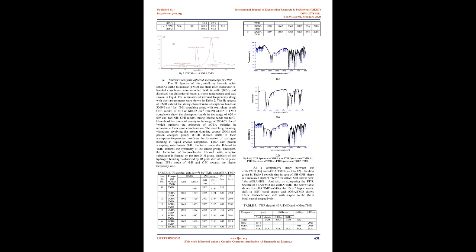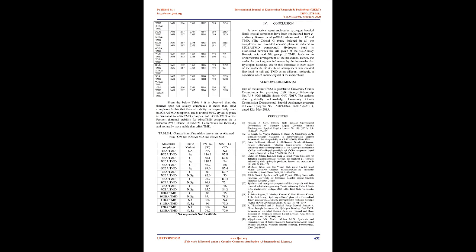Crystal G phase 27 consists of molecules packed in different layers with the long axis tilted with respect to the normal layer planes, characterized by a C-centered monoclinic cell with tilted molecules having pseudo-hexagonal close packing 27. The thermal span of all the crystal G phases induced in the complexes ranges around 100 to 200 C, which is a remarkable feature of these samples. The thermal span of the nematic phase was reduced from the pure mesogens, nOBA.